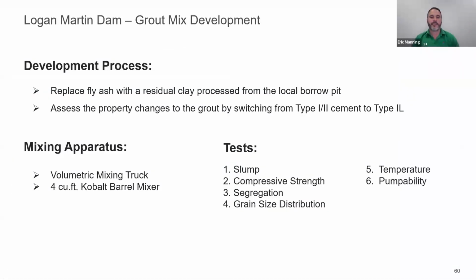So as I mentioned, recently we started this grout mix development program, testing our conventional type 1-2 cement mix and comparing that to our type 1L. The purpose of this was to replace the fly ash and substitute it with the local residual clay that's processed from our local borrow pit.